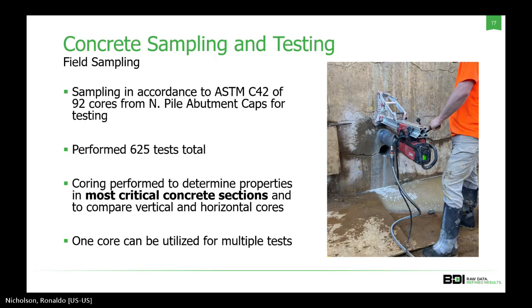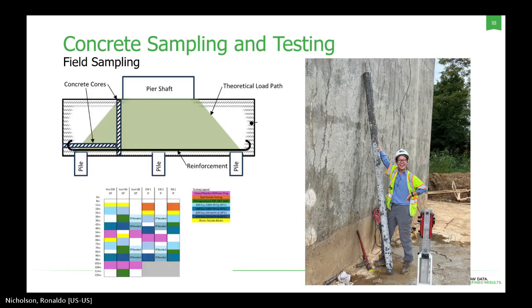So for the concrete sampling and testing, we sampled in accordance with ASTM C42, and we collected about 92 cores across the entire north approach, where one core could be utilized for multiple tests since these were going to be pretty large cores. We performed about 625 tests total, and we decided on collecting the cores in the most critical concrete sections, for both vertical cores and horizontal cores. And I'll explain a little bit of what that means in the next slide.